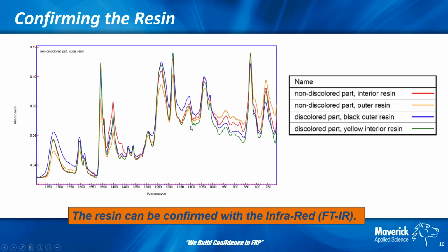So what you see here is basically an infrared scan, and the lines here show the internal resin. The outer resin, which is non-discolored, would be furthest to the outside, and you see the black outer resin, and then you also see this discolored part, and you see yellow resin. They're not perfectly overlaying, but largely following the same signal on the waveform. That basically tells us that the resin is the same throughout. The corrosion barrier resin is the same as the structural resin.